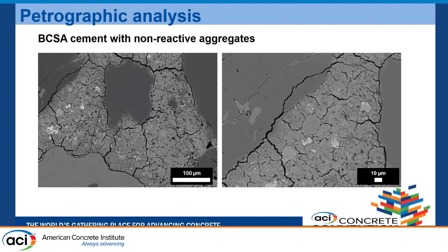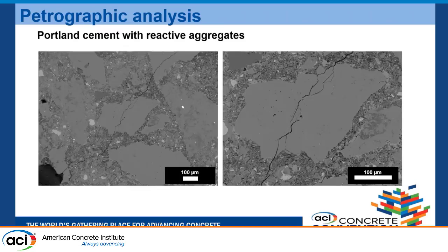Here you see an image of BCSA cement specimens with non-reactive aggregates. Again, the majority of the cracks are focused mostly in the paste region, and even though there are some cracks through the aggregate, they are mostly concentrated towards the periphery and not a typical ASR crack through the aggregate. Again, what we can say is that it is a result of the desiccation from the drying process and not a clear indicator of ASR.